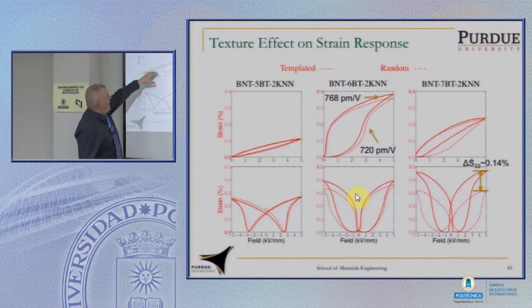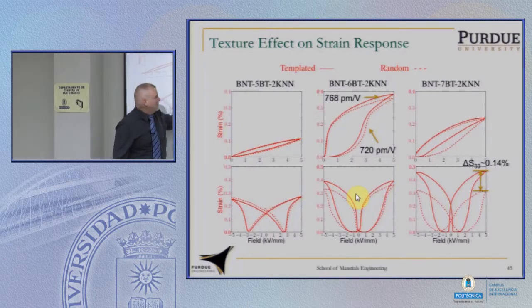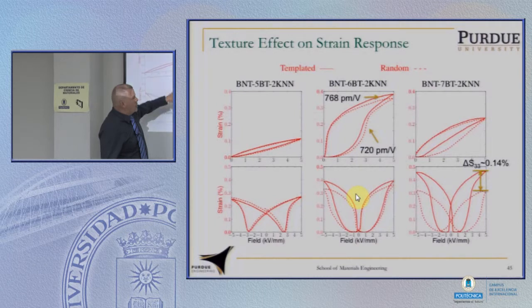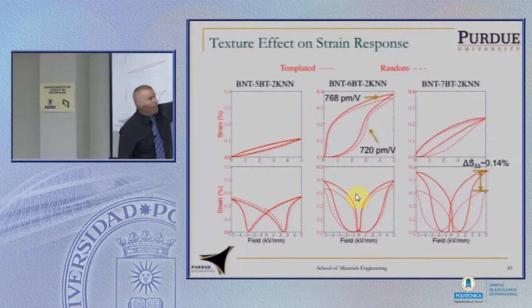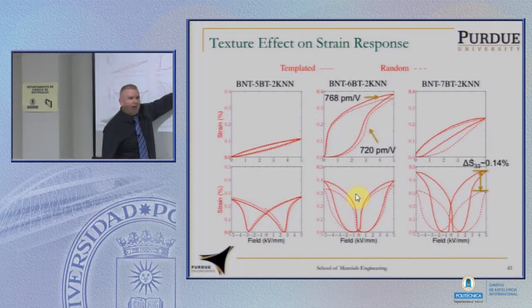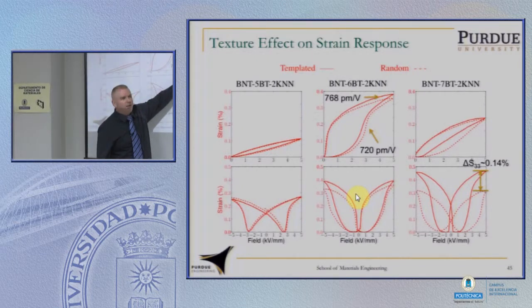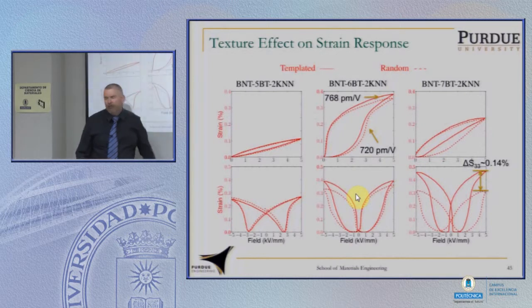The behavior for the random material is shown as the dotted line, and the behavior for the oriented material is the other. And these were not strongly oriented pieces, but you see a difference in the behavior. So you see more strain. And you see more strain in the bipolar test than in the unipolar test, which surprised us. Okay.